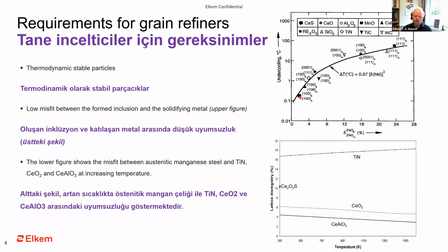While if you look at this one down here, which has a very low misfit, it requires very low undercooling, then we are at cerium sulfide. And we also see here, for example, that in general, rare earth oxides require very low undercooling and have a very low misfit. And if we look at the figure here on the right, it shows the misfit between austenitic manganese steel and titanium nitride, cerium oxides, and cerium aluminates at increasing temperature. So here we have on the y-axis the lattice disregistry or the degree of misfit, and on the x-axis the temperature in Kelvin.